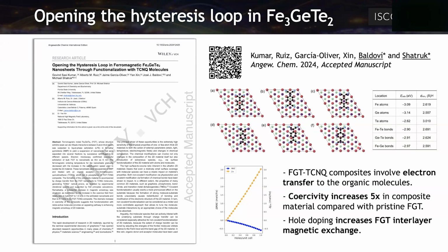And we observe in this case that electron transfer is very important in this material. This makes the coercivity of the iron germanium telluride increase 5 times. And when we have this hole doping, we are increasing the exchange interactions that are interlayer, between the layers. So this is the main reason, and it's not an effect in the magnetic anisotropy energy, the key in this structure. So this is the last work that we have been working on in the last months.